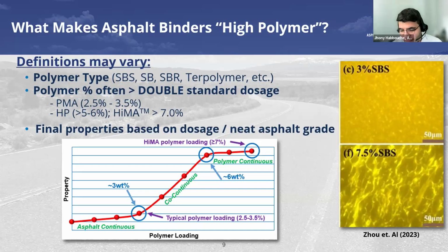Like at the beginning, what Nam was talking about, the HiMA sections, they involved HiMA binder that had about 7% of Kraton's SBS polymer there. I want to emphasize, and I'm going to re-mention that towards the end of the presentation, the definition of high polymer is not and should not be based on polymer content, but this is one of the features that could direct towards characterizing a binder by calling it a high polymer.